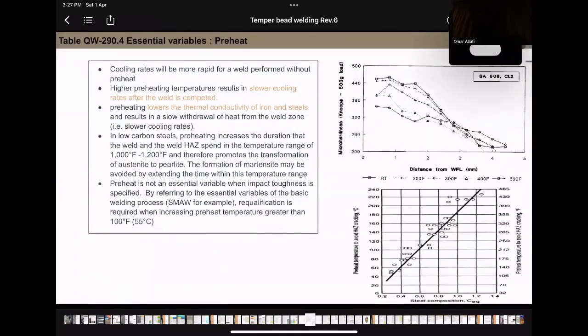Preheat. So as I said, preheat is good for hardness and not good for controlling toughness. So preheat temperature is an essential variable when hardness is specified. That's why it is an essential variable for method A, which is hardness. So a higher preheating temperature results in slower cooling rates. So when you start with a higher temperature, the cooling rate will be slower. Why? Because it lowers the thermal conductivity of iron and steel.